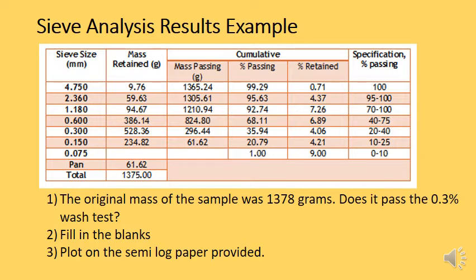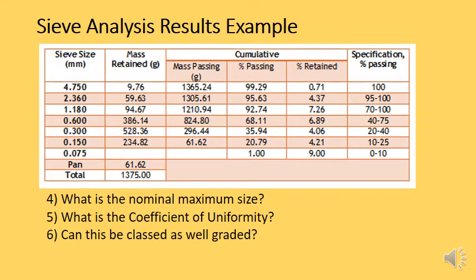Following that, we can take that final column and plot it on the semi-log paper provided. Another question we need to ask ourselves following the logging and making that graph is, what is the nominal maximum size? What is the D95? Also, what is the coefficient of uniformity? Well, first off, let's do question 4 here. The nominal maximum size is where 95% of the aggregate is smaller than this. Well, we can look at the percentage passing column and we can see that 95.63% of the aggregate is smaller than 2.36 millimeters. So the nominal maximum size will be about 2.3 millimeters roughly, or maybe 2 millimeters.